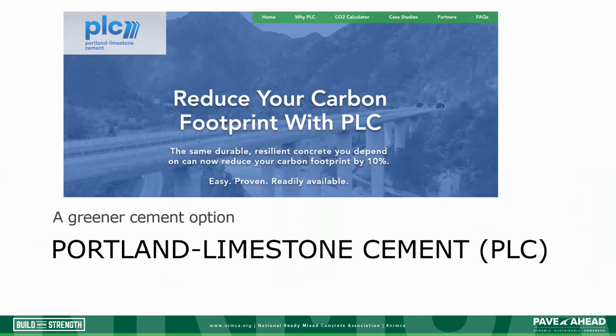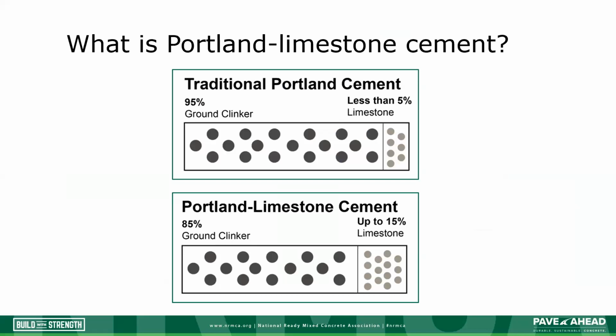The first thing we'll look at is Portland-limestone cement. It's a blended cement with additional limestone content, which is optimized for performance. While regular Portland cement contains up to 5% limestone, Portland limestone cement is made by intergrinding 15% limestone with a reduced amount of regular clinker, the main energy-intensive ingredient in Portland cement. Remember that we said 50 to 60% of the CO2 produced was attributable to calcination of calcium carbonate. Reducing the amount of clinker per ton of cement reduces the amount of attributable carbon dioxide. Portland limestone cement is a finer ground product than regular Portland cement. So the smaller size produces a particle packing effect that increases the resulting concrete strength.